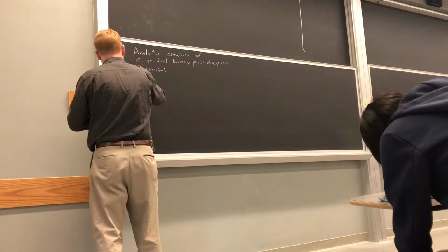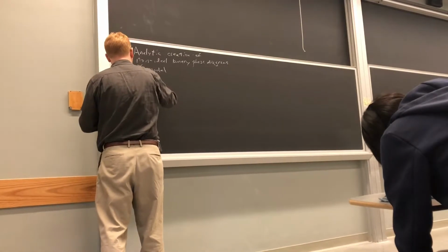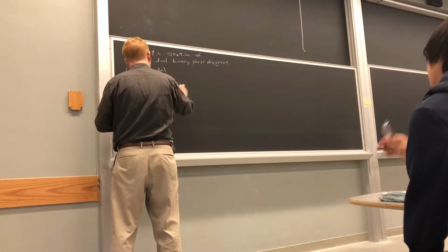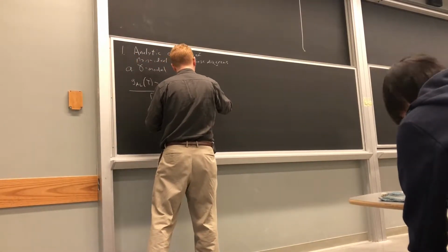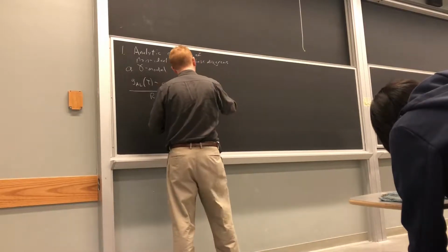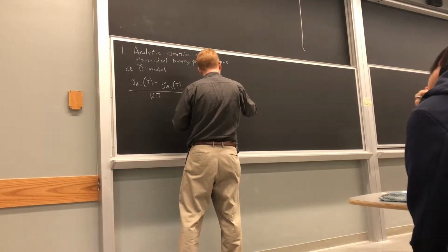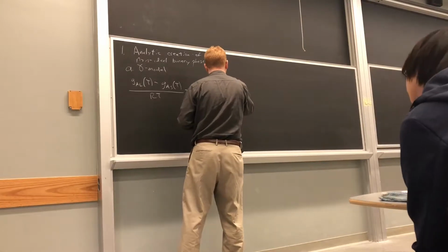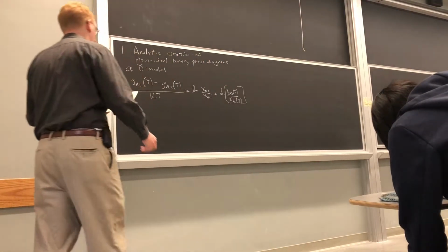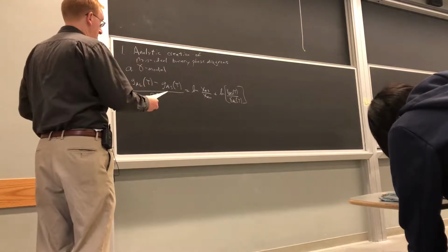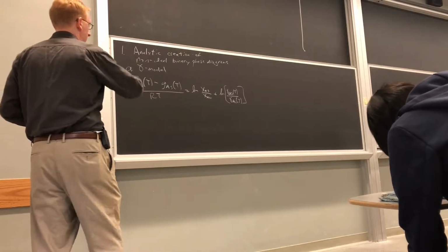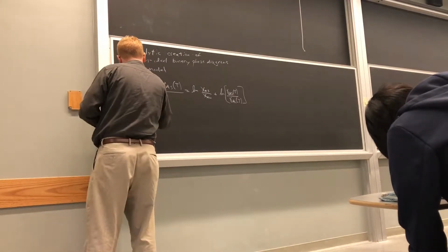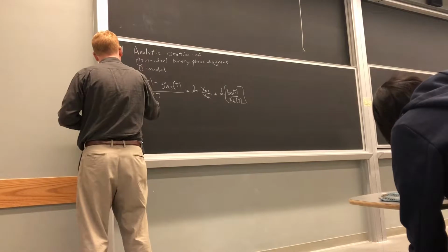So from the homework we had G_A of the liquid as a function of T minus G_A of the solid as a function of T divided by RT, which is equal to the natural log of X_A of the solid over X_A of the liquid plus the natural log of gamma_A of the solid as a function of temperature divided by gamma_A of the liquid as a function of temperature, where I've used the property of the natural logarithm to separate out those terms. And then you do the same sort of thing for B, with all the A's replaced with B's. So same for B.